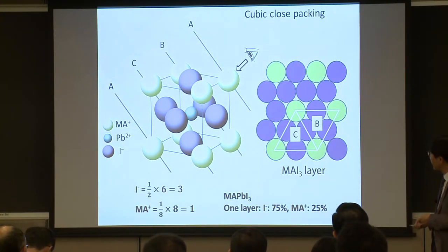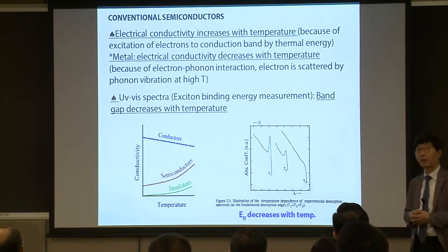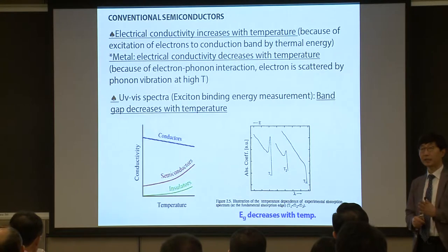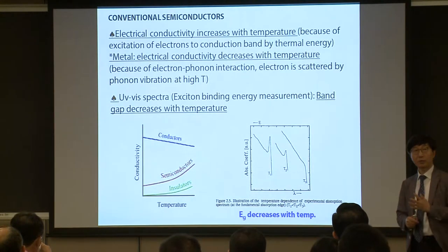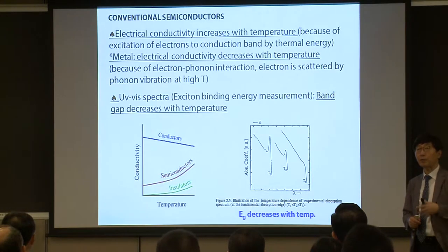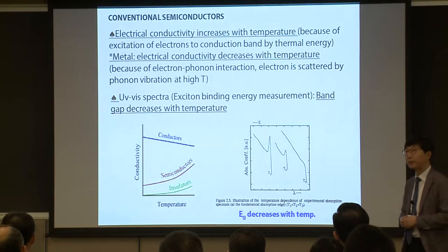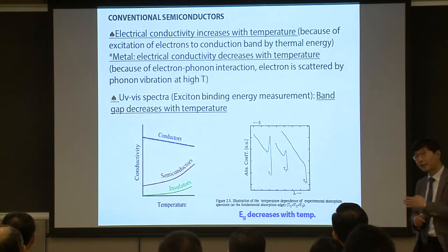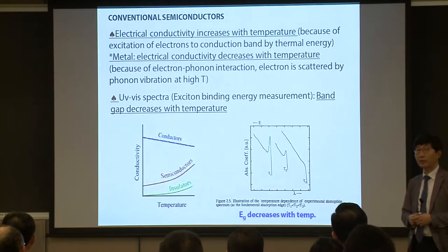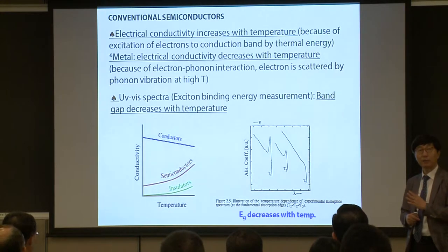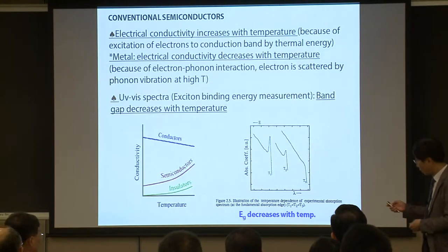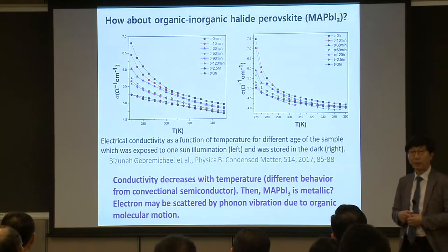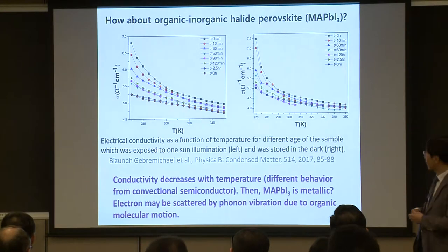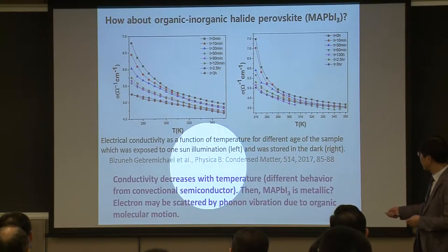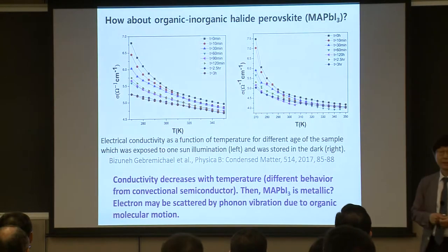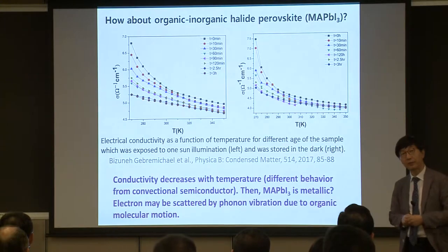For a conventional semiconductor, we can expect electrical conductivity to increase with temperature because of the increase in the population of excitation by thermal energy. But for a metal, the electrical conductivity decreases with temperature because the electrons are scattered by phonon vibration at high temperature. For instance, for MAPbI3, this data is taken from a journal paper, and the electrical conductivity decreases with temperature.